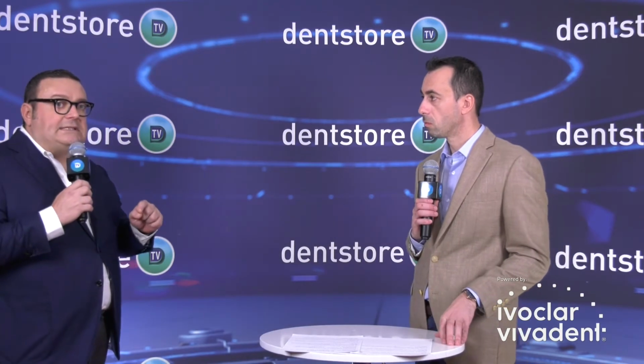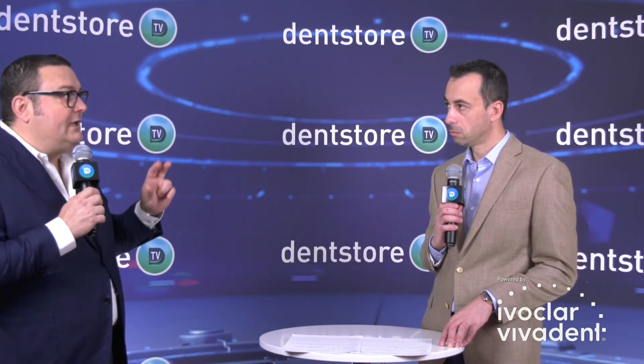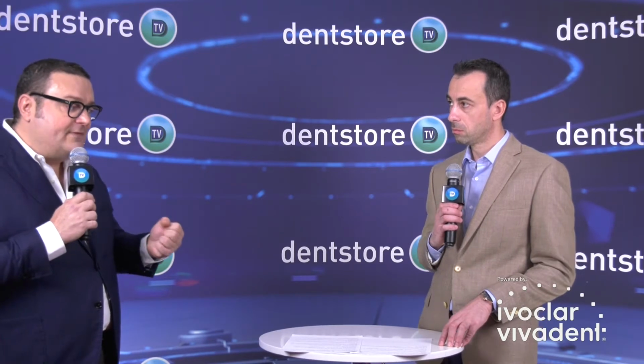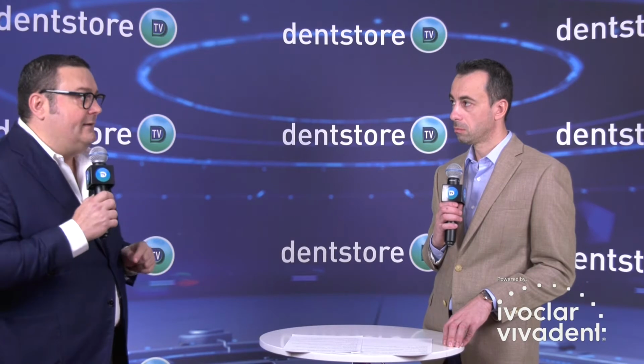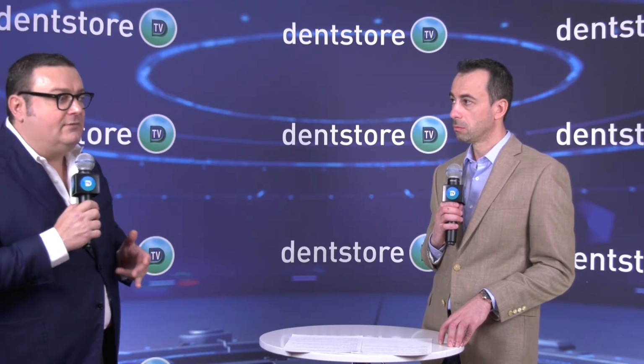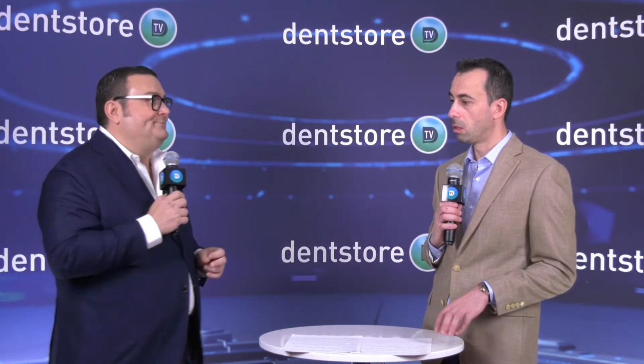You can treat this kind of situation with air polishing, that is completely different to sandblasting, with powder, not glycine because it's not so effective. I prefer to use sodium carbonate 30th generation because it's much faster and more effective, without any risk to insult the hybrid layer. And immediately after the isolation, I can sandblast to increase the mechanical retention of the overlay on the top.